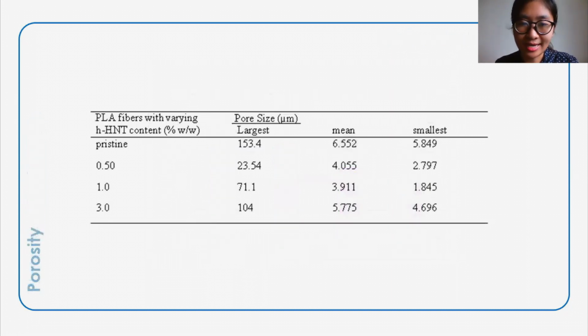Next is assessing the pore size of electrospun composite mats, which connects to the material's air permeability. An increase of HHNT content revealed increasing pore sizes. Mean flow pore sizes of 3 to 6 micrometers may provide breathability at the wound site, allowing oxygen molecules to pass through the electrospun fiber mat. At 1% HHNT content, it has the lowest mean pore size, and its smallest pore size is also 1.8 micrometers. The smaller the pore size, the better, so that it can block harmful microorganisms from entering the wound bed. The average size of most bacteria, however, is between 0.2 and 2 micrometers in diameter. So for this material, PLA with 1% HHNT content, it is only partially effective as a barrier to prevent microorganisms from entering the wound site.